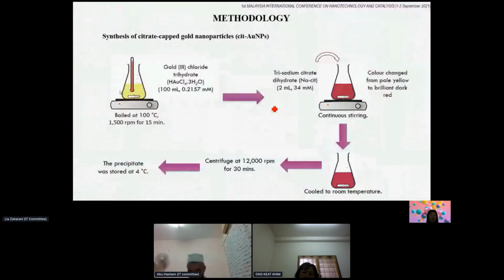This slide shows the synthesis of citrate-capped gold nanoparticles. At first, we add gold(III) chloride trihydrate into a conical flask, then boil at 100 Celsius for 15 minutes at 1500 RPM, followed by adding trisodium citrate dihydrate into the solution. The color will change from pale yellow to dark red, which indicates the formation of gold nanoparticles. Then let it cool down to room temperature before centrifuging at 12,000 RPM for 30 minutes. And then the precipitate will be collected and stored at 4 degrees Celsius.